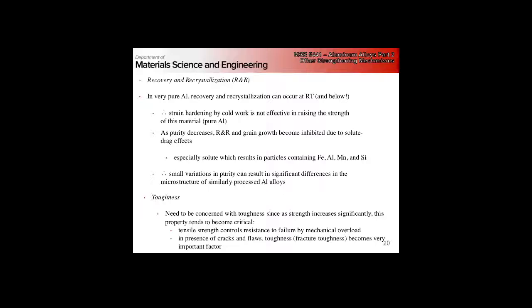right? And tensile strength happens to be inversely proportional to toughness, right? And just as a quick reminder, tensile strength is resistance to failure by mechanical overload, right? Toughness really here, the fracture toughness, is the energy under the stress strain curve, right? And in the presence of flaws or other defects, can drastically reduce the amount of energy that we absorb or dissipate. So in aluminum alloys, we have ductile failure, right? Which means that we sort of get voids that nucleate and coalesce, and you get these fibrils, right?